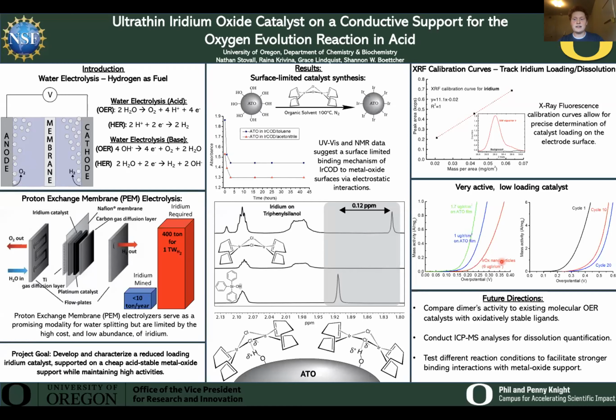We also wanted to test the stability of our catalyst through many cycles of cyclic voltammetry, as that has been the problem reported in the literature, that these ultra-thin catalysts are not very stable. And we found something similar, where cycle 1, you see here, it was very active, but over time, we saw a later and later onset of current, which denotes later and later onset of our oxygen evolution reaction.